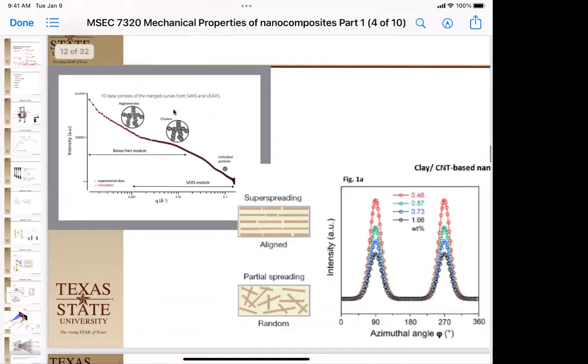All right, questions on small angle versus wide angle? So just to clarify, a fully exfoliated sample would essentially have no peaks. A fully exfoliated sample that is randomly oriented would have very few peaks, just a broad line. But if there's any order at all, and there's tons of ways to induce order, you will start to see these. And if you have the tactoids that are partially intercalated, you're going to see a wider spacing than the clay by itself.